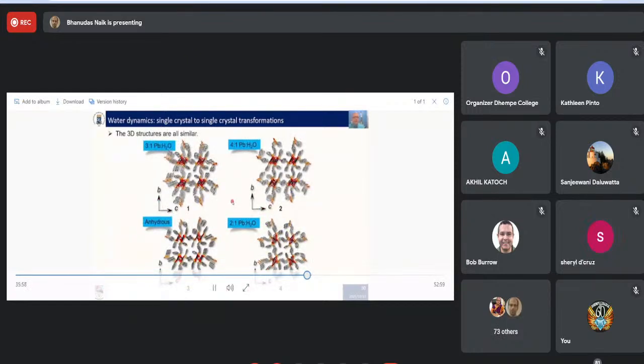And if you look at all four of these compounds, you can see they're all basically the same. You have the same sort of structure where you have the central phosphonate bridges, and you have the longer organic spacer bridges between the two. So you have the anhydrous compound, the 3-to-1 lead to water, the 4-to-1 lead to water, and the 2-to-1 lead to water, all very similar.